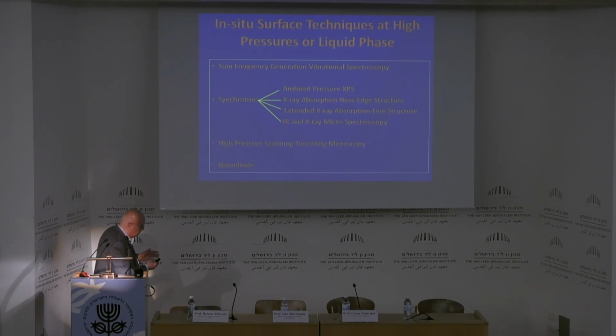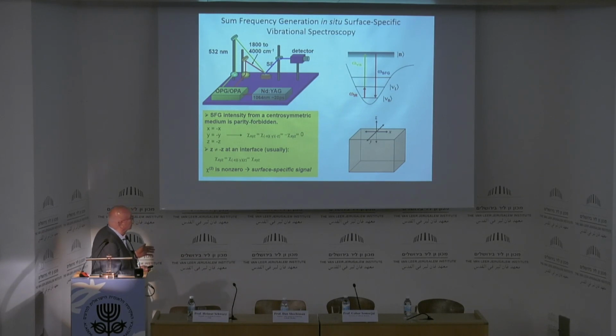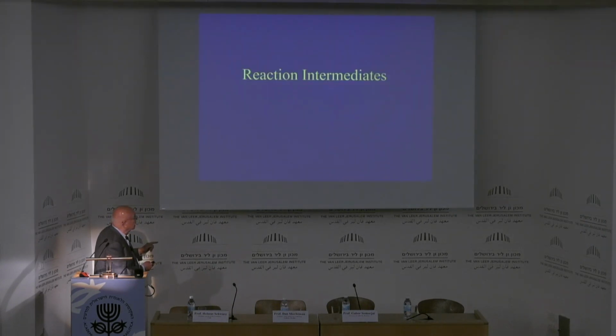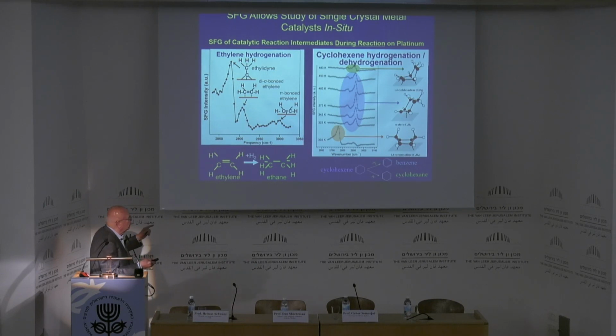Now, the technique that Berkeley developed was the sum frequency generation vibrational spectroscopy that is surface sensitive, because this omega 1 plus omega 2, sum frequency at 2 different frequencies, is forbidden in the centrosymmetric environment. And so the surface is not centrosymmetric, and so it gives you a surface technology to determine what's happening on the surface under reaction condition. Here is an ethylene hydrogenation reaction, and what you see are 3 peaks, and these 3 peaks are showing the